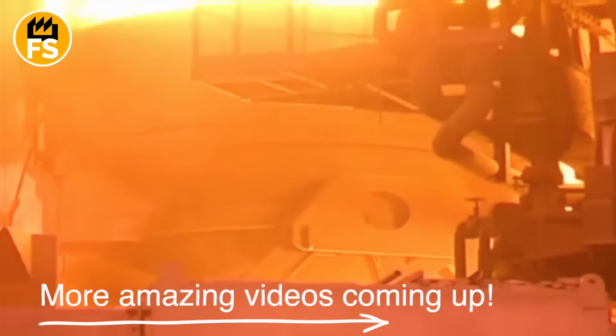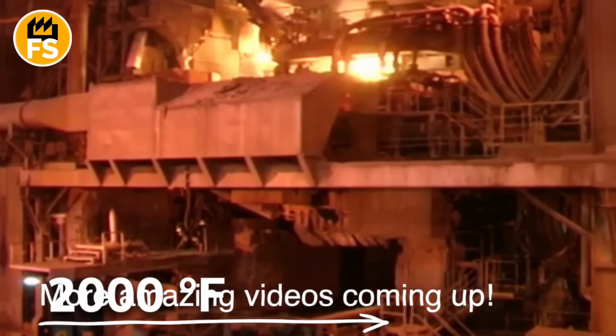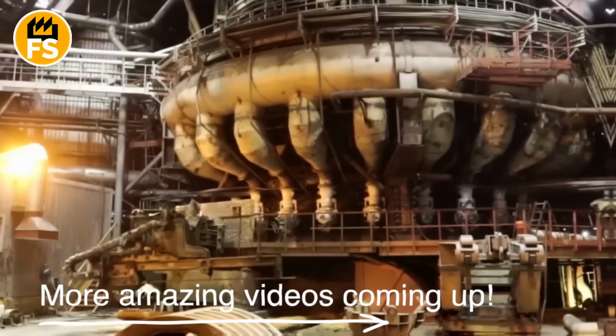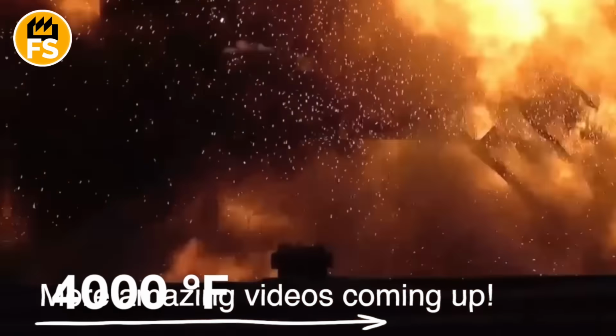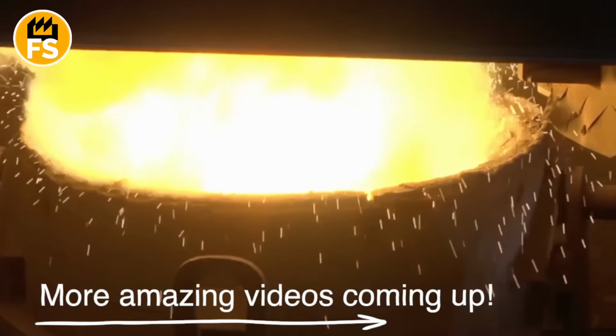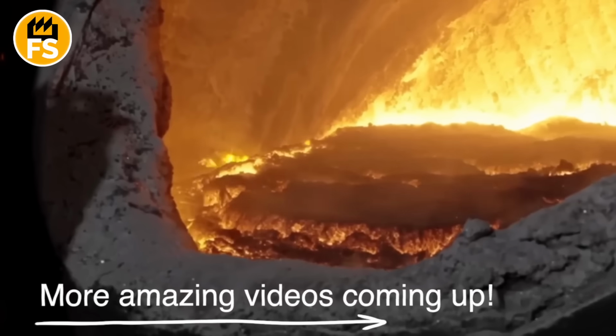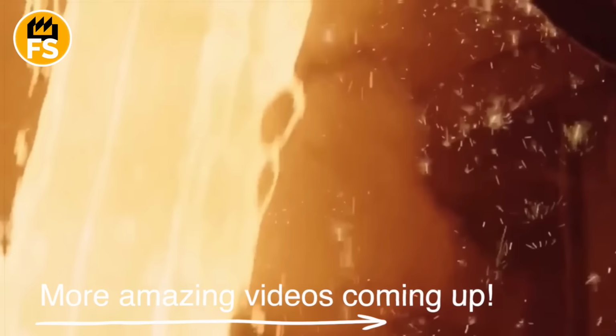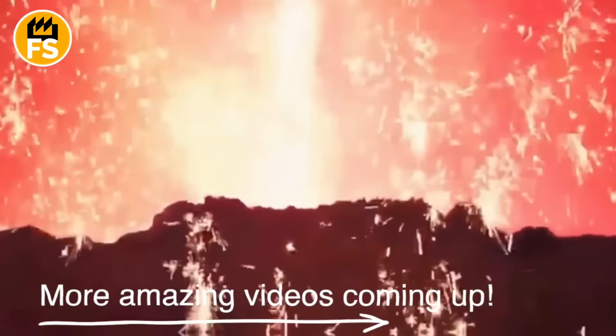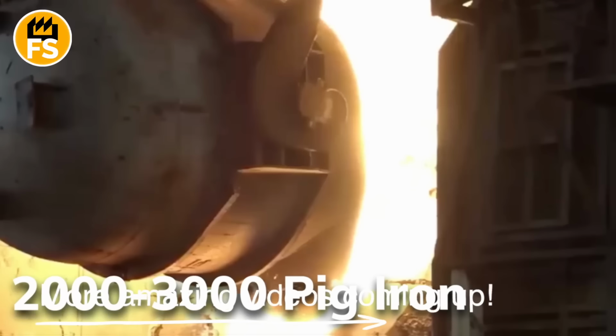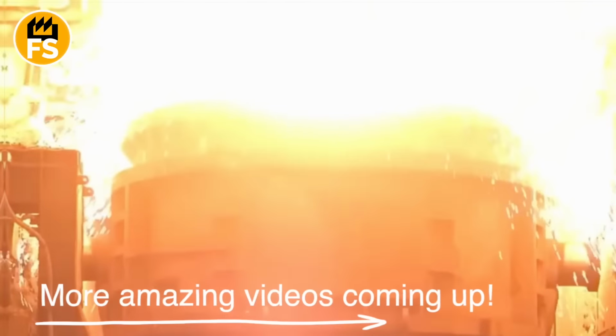Hot air, heated to 2,000 degrees Fahrenheit, gets blasted in from below. The coke burns. The temperature inside the furnace hits 4,000 degrees. At those temperatures, carbon rips the oxygen away from the iron oxide. The iron melts and flows to the bottom of the furnace. The scale of the process is staggering. A single blast furnace consumes 3,000 to 5,000 tons of ore per day, about a ton of coke, and produces 2,000 to 3,000 tons of pig iron. That's iron with high carbon content, around 3 to 4%.